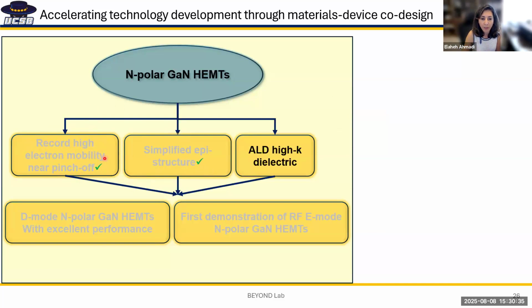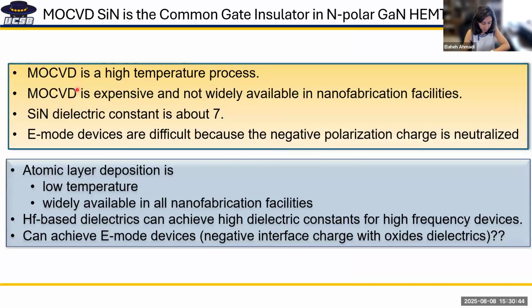But while we were working on developing the material, at the same time we wanted to look at alternative dielectrics, because as I mentioned, MOCVD is a high temperature process. It is expensive and not widely available in nanofab facilities, and the dielectric constant is relatively low, about 7. And also, E-mode devices are difficult because of the negative polarization charge that is neutralized by silicon nitride. So when we started, we were interested in developing dielectrics by ALD, which is a low temperature deposition technique and widely available, and hafnium based dielectrics to see if we can get higher dielectric constants. We were also interested in E-mode devices, and we wanted to see if having an oxide dielectric makes a difference, and we can do that easier.